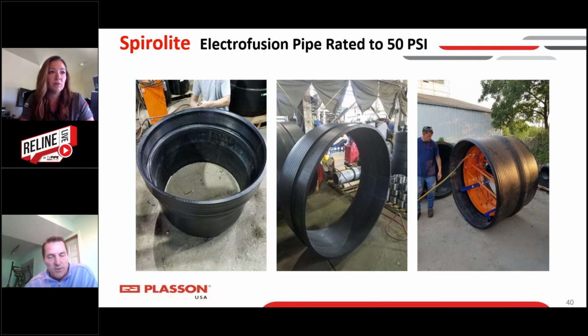Now we're testing each individual joint. We have the ability to test each individual joint on these projects. And we tested that pipe to failure. And as it did, the pipe yielded and not the joint. That's what should be done in Electrofusion design.